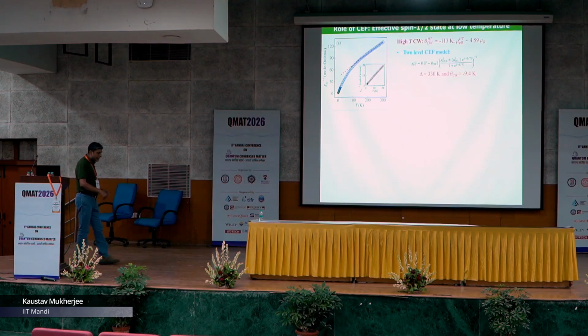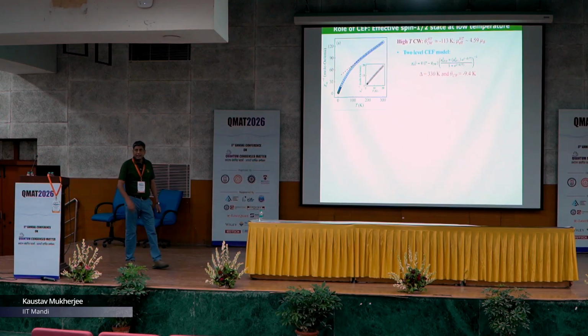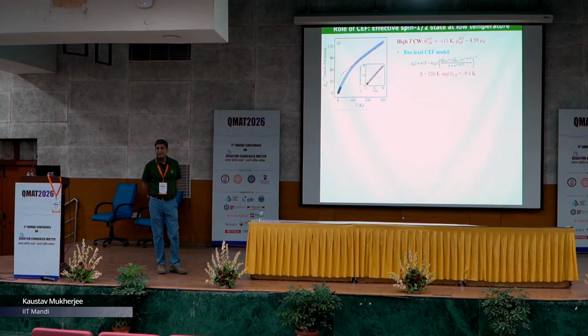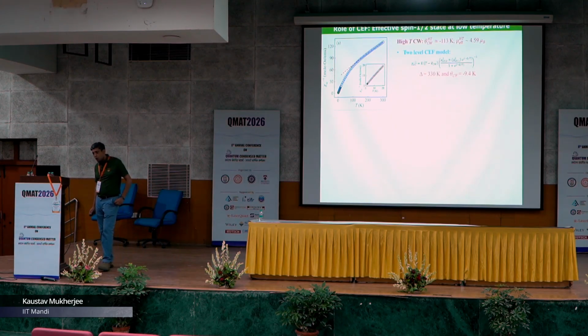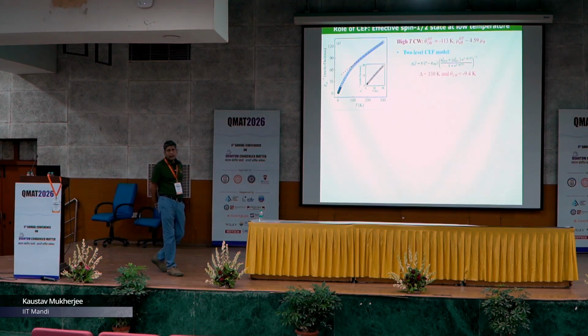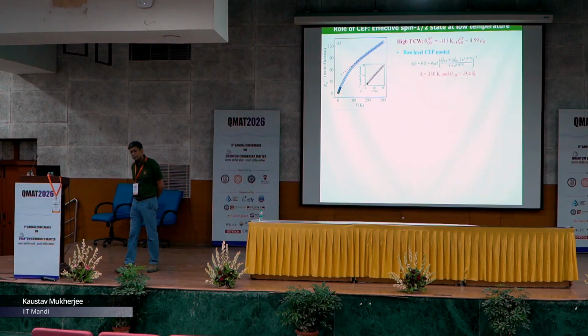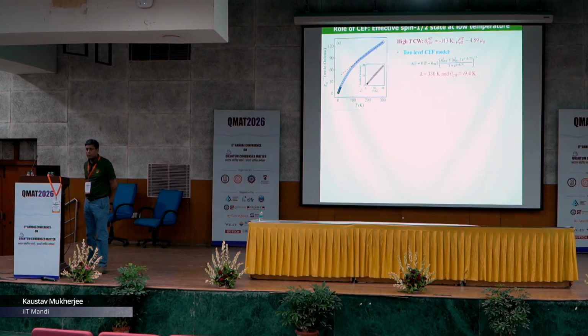To get a better idea of the magnetic state of this system, inverse susceptibility is plotted as a function of temperature and it was fitted with the Curie-Weiss law. What we saw is that the curve, that is the red line, fitted well above 120 Kelvin, but below 120 Kelvin a deviation was observed. But the obtained magnetic moment was around 4.6 mu B, which is almost in agreement with the theoretical magnetic moment of the Yb3+ ion.